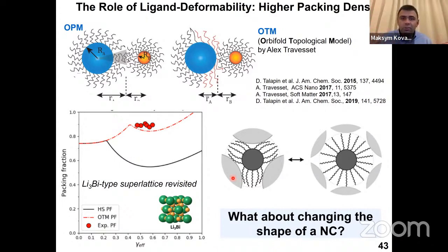So if that happens, you can expect that your overall stability of the lattice will be higher because you can stuff much more material per unit volume. And for spheres, this has noticeable effect only in those structures where you have small coordination numbers. If the coordination number is high, there is simply no space to bend away these ligands.